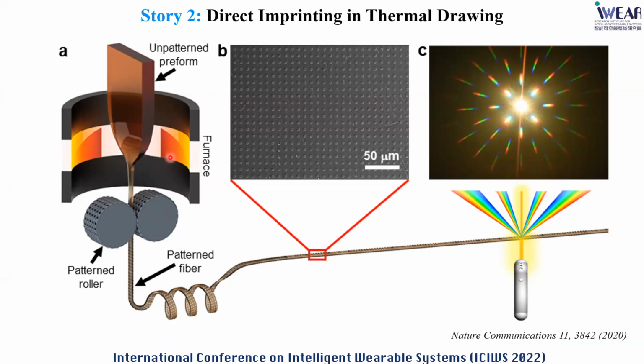So what we did is that during the thermal drawing process, we try to have those so-called patterned rollers. When the fiber is out of the furnace, the fiber is still soft, as we mentioned, this is the transition from solid to liquid and liquid to solid. So it's still soft, and in that case, we use those patterned rollers to transfer the patterns from the roller onto the outer surface of the fibers. Because this is a continuous fabrication, we will be able to cover the entire surface of the fiber with those micro scale and also nano scale patterns.